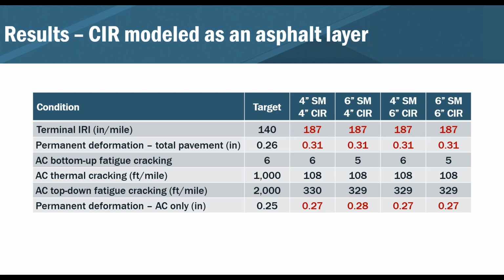VDOT limits resilient modulus value to 15,000 PSI for design purposes. For this example, we're using 16,000 PSI. Is this a change from VDOT's manual? A change of 1,000 PSI. So the value that we used was the value that was provided in the DGPX file. So we didn't change anything from what Harry had analyzed. Right.